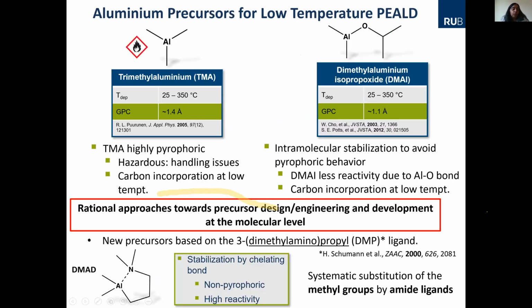So when you want to grow aluminum oxide, as I said, the precursor chemistry plays an important role. Commercially available precursors for aluminum, for example, trimethyl aluminum. It's a very volatile compound. If you open the bottle, it will burn in air. It's highly pyrophoric. It has a very good reactivity, very good for ALD. But the issue is that it's hazardous, as I said, and also because at low temperatures of deposition, the carbon moieties present in the ligand can also get into the film, which can affect the functional properties.